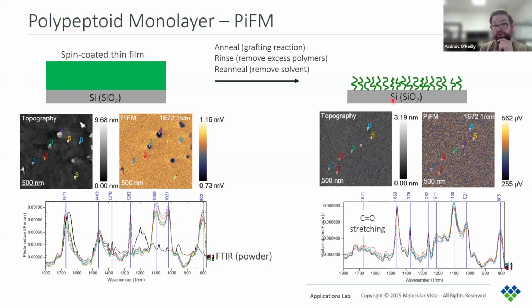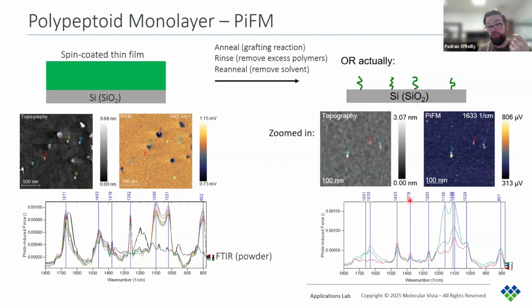Now, when we look at the monolayer samples, we see there's no evidence of this carbonyl peak. There are some siloxane peaks again and some CH peaks around 1460 and 1380, but definitely not a homogeneous peptoid monolayer. But when we zoomed in a bit more, we see that there actually are some peptoid molecules on the surface. While some of them are difficult to see in the topography, they can be seen in the PiFM image here at 1633, these slightly brighter regions in this chemical map.